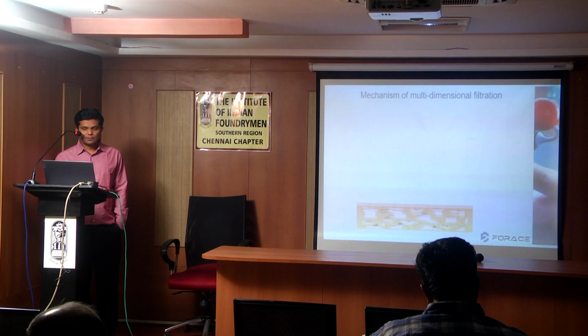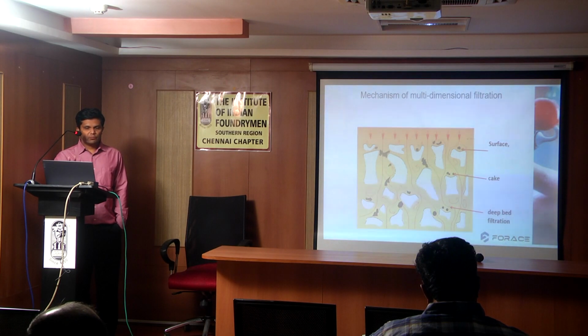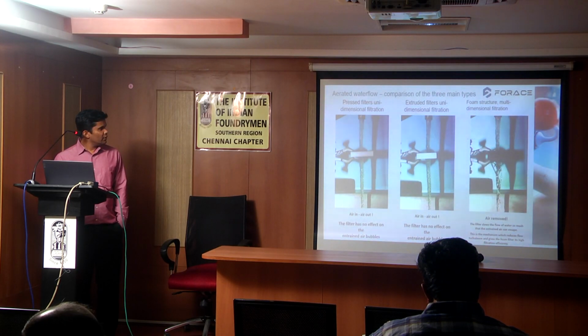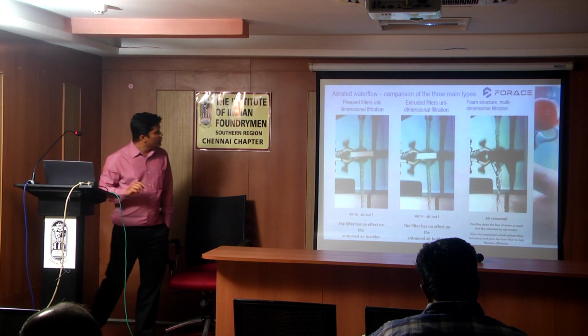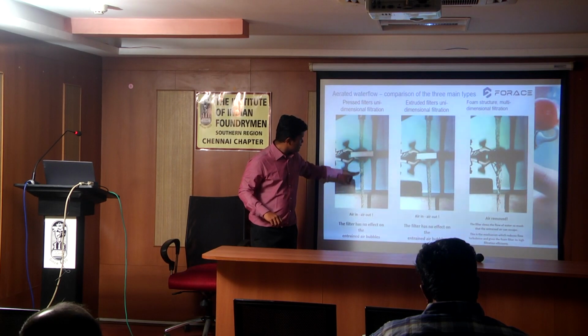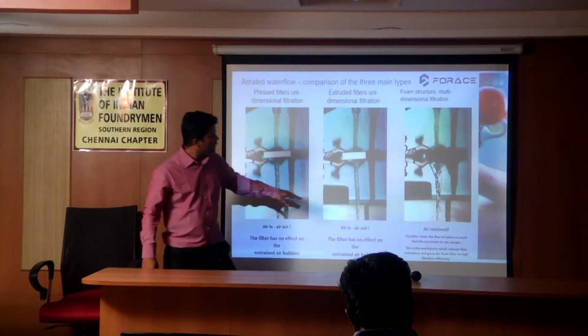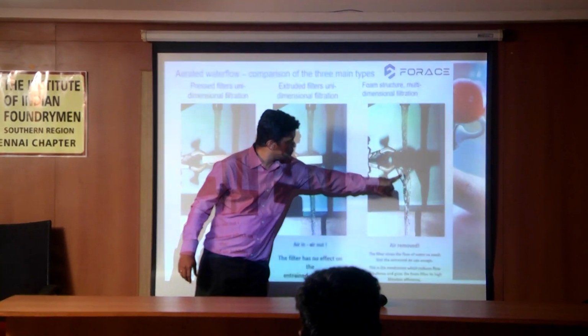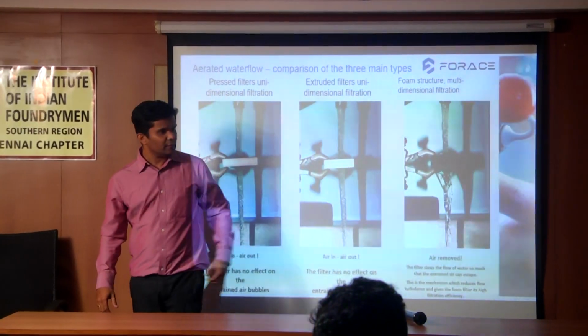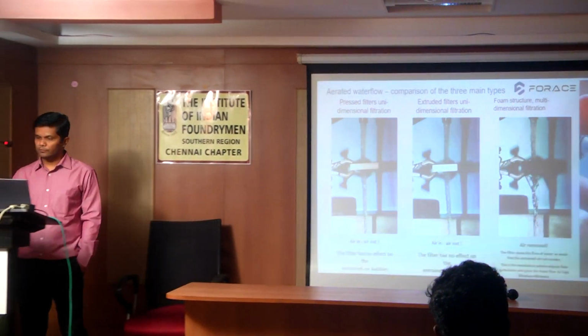So these are the foam filters. This is the working principle. They have different pores inside, so even the minor slag or inclusion particles will get trapped. Here we have done some experiments in comparison of the foam filter and the press filters. We sent some aerated water, and you can see the same aerated water is coming out. But with the foam filter, the clear water comes out, and all the air bubbles have been trapped in the filter.